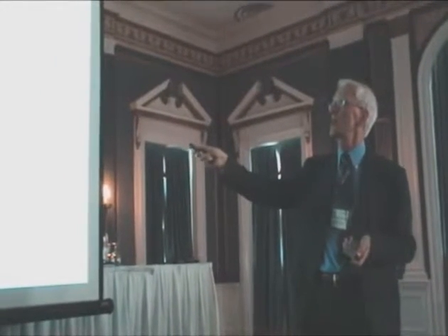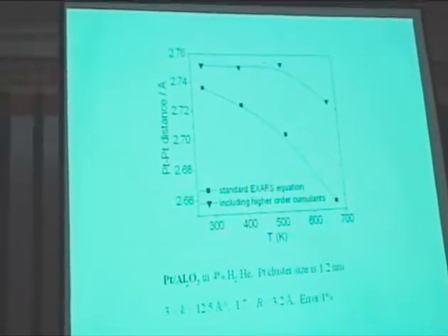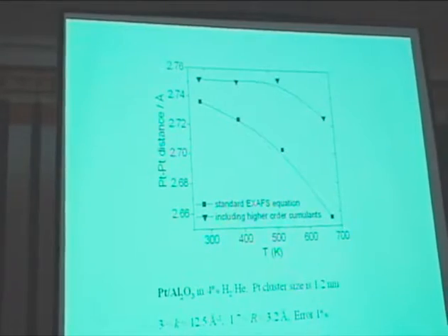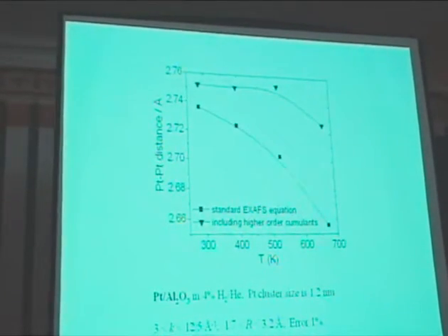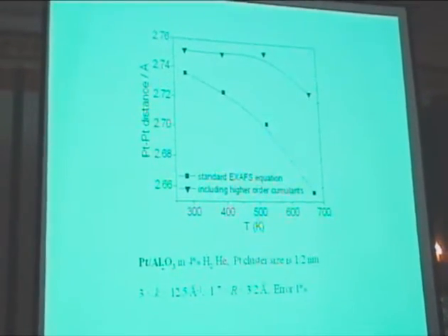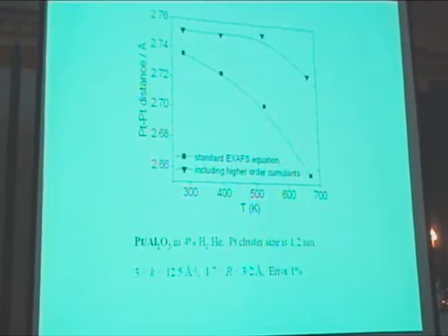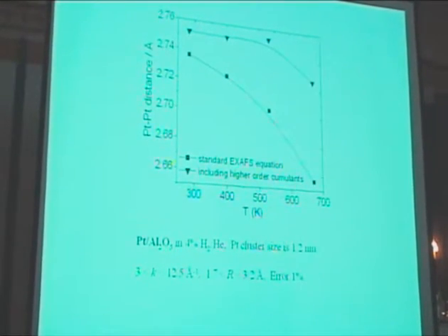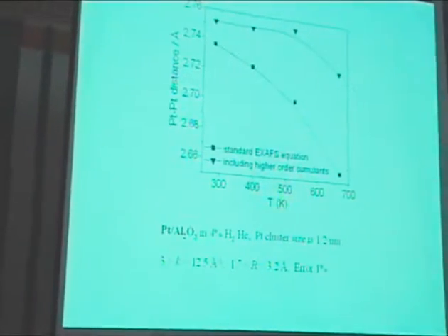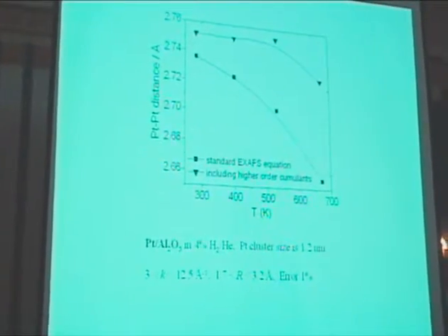It's this part which shows the higher cumulants must be there, showing that this small metal particle, and it's not unexpected, should be treated in the theory with higher order cumulants, in other words, with a skewed distribution. And again, this has to do with the fact that the distance from the atoms at the surface to the ones below is shorter than the platinum-platinum distance in the middle of the particle.